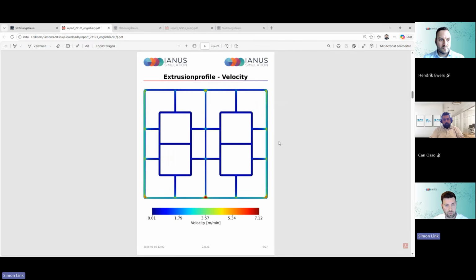So we also see these velocity hotspots, what I call them, and this can be a problem, of course, in the manufacturing process if we don't have this more or less uniform velocity. So we can then go back into our tool design and make adaptations. So we can detect areas, and maybe in the middle we can decrease the resistance of the flow, and on the outside we can also make adaptations to reach a more uniform material velocity.